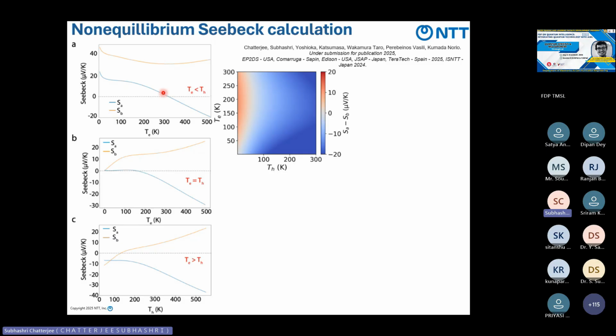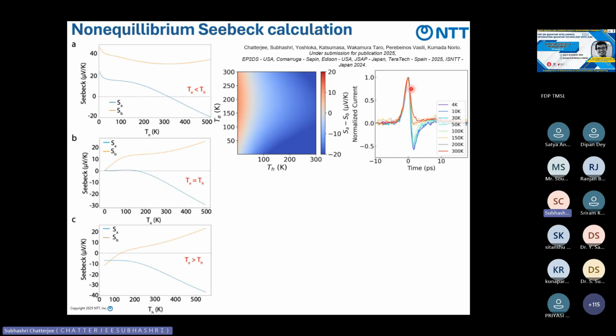we can see that Se minus Sh is positive for this condition and this condition. But when the electron temperature is higher than the hole, we can see the Seebeck coefficient flipping its sign. So we confirm that due to this condition, the Seebeck is changing its polarity, and hence we are getting two peaks from the changes in the Seebeck coefficient.